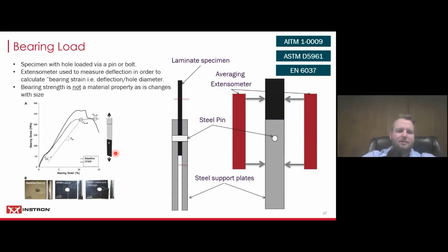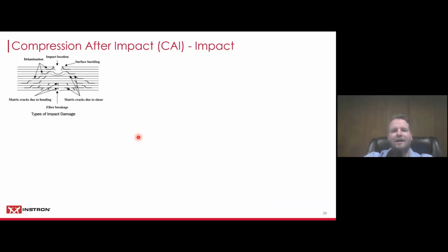And down here you can see some typical failures. You need to make sure with this test method that you have the failure actually in the hole. And there's a couple of different allowables, which is really typical for composites testing standards. They typically have a variety of allowable and not allowable failure modes. So always check that. If you don't get the right failure mode, you're not in compliance with the standard. And now compression after impact, another one we need to look at here.